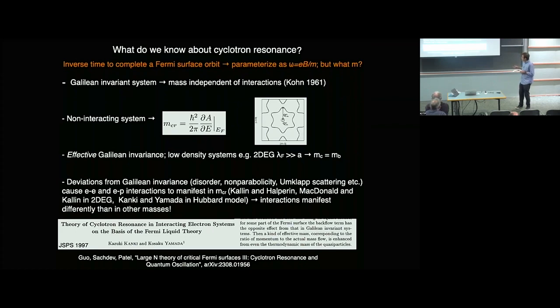There is this paper here, perhaps relevant to the cuprates, by Kanki and Yamada, that did a simple calculation, but motivated by the Hubbard model. And as they point out, a kind of effective mass corresponding to the ratio of momentum to actual mass flow is enhanced from even the thermodynamic mass of the quasiparticles. And so they point out that you can get different masses from a system like this when there's Umklapp scattering.